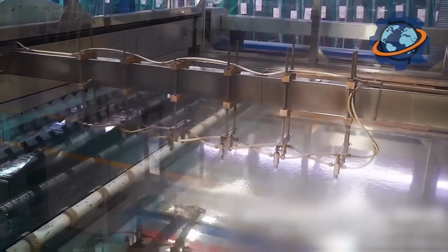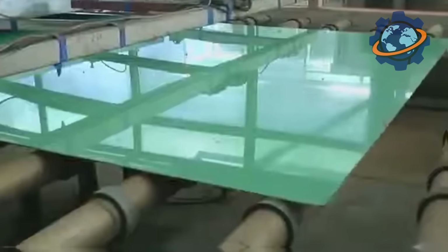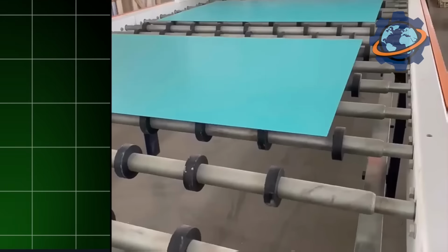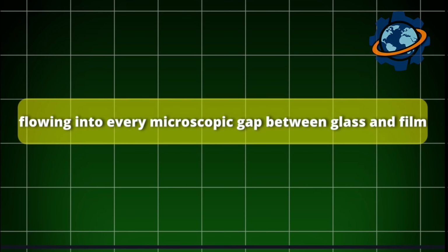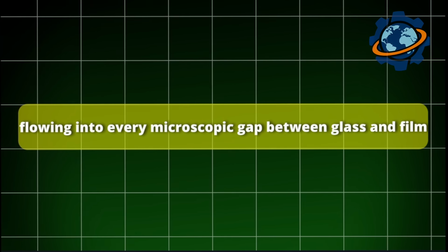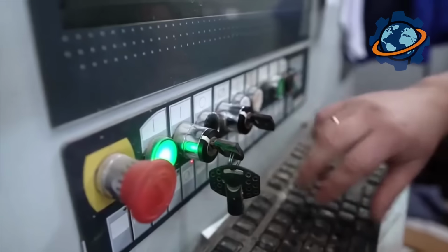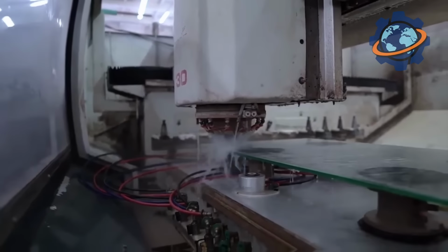Picture autoclave loading. Workers stack 50 windshields on racks separated by spacers. The door, thick as a bank vault, swings closed. Temperature rises to 150 degrees while pressure climbs to 200 psi. Under these conditions, PVB melts slightly, flowing into every microscopic gap between glass and film. Chemical bonds form. After 90 minutes, the layers become inseparable. What exits is a single unit, a glass-plastic-glass sandwich, impossible to separate without destroying.